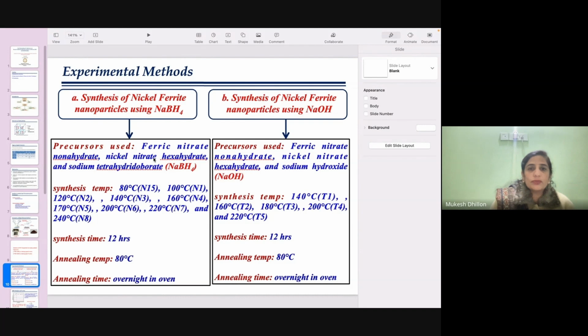Here precursor used are ferric nitrate nonahydrate, nickel nitrate hexahydrate, and reducing agent we use NaBH4. And synthesis temperature variation is 80 degree, 100, 120, 140, 160, 170, 200, 220, and 240. And naming is also with these temperatures. Synthesis time is 12 hour, annealing temperature 80 degrees Celsius, annealing time overnight in oven.